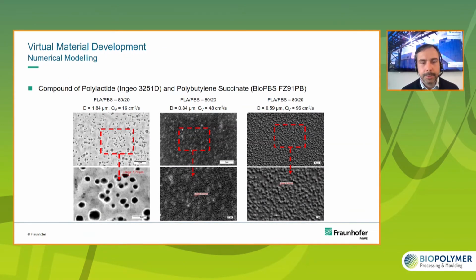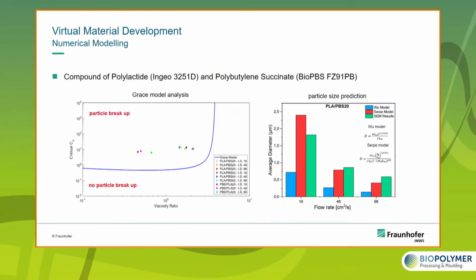And for us, this is very important information because this will clearly change the mechanical properties of our material. So based on these results, we did the capillary number calculation for our blend of PLA and PBS, and this is what you can see here. On the left side, you can see that the capillary number for all of those blends during injection molding was above the critical capillary number. This means we had breakup of our droplets during the process. And of course, this has an influence on the properties.